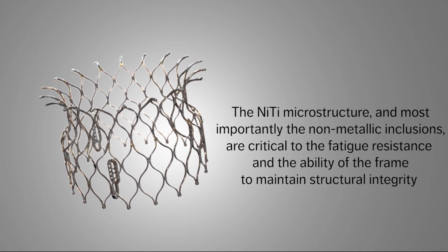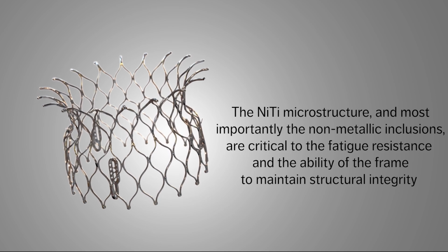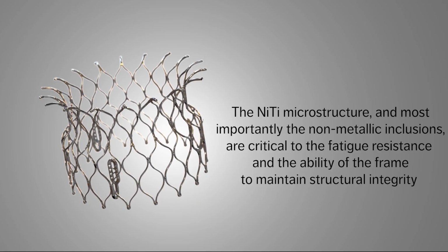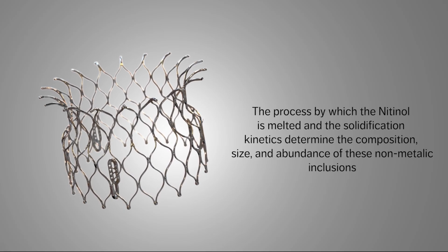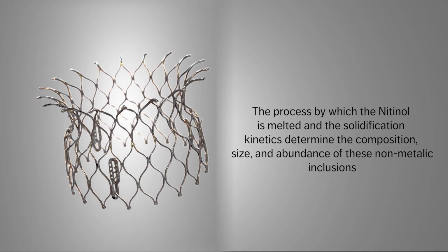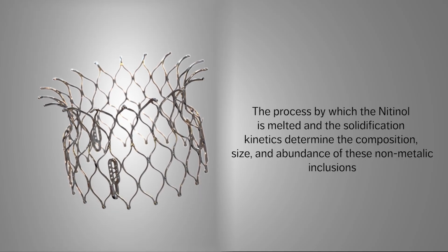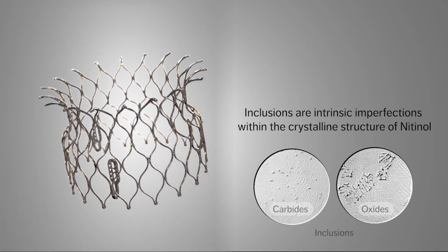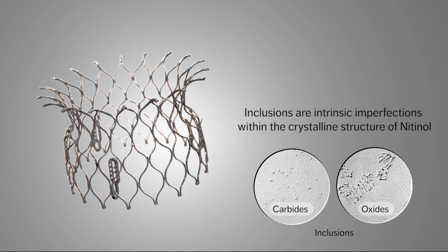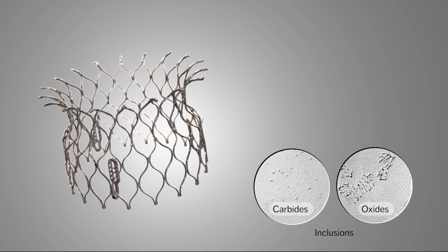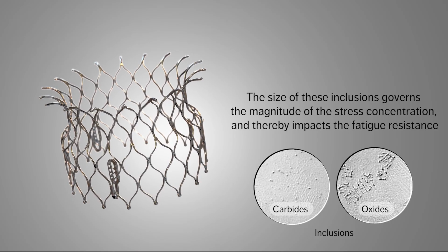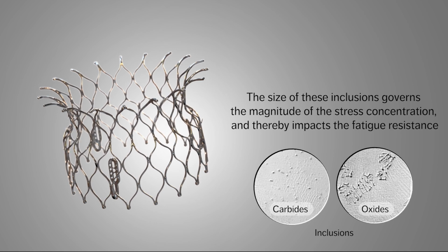The nitinol microstructure, and importantly its non-metallic inclusions, are critical to the fatigue resistance and the ability of the frame to maintain structural integrity. The process by which the nitinol is melted and its solidification kinetics determine the composition, size, and abundance of these non-metallic inclusions. Inclusions are intrinsic imperfections within the crystalline structure of nitinol. The size of these inclusions governs the magnitude of the stress concentration and thereby impacts the fatigue resistance of the structural form, a heart valve frame in our example.